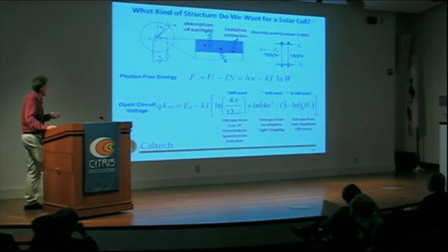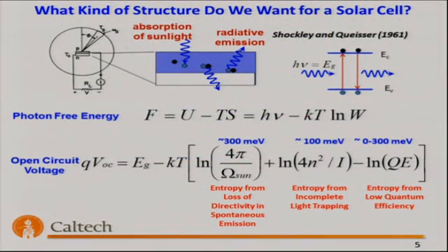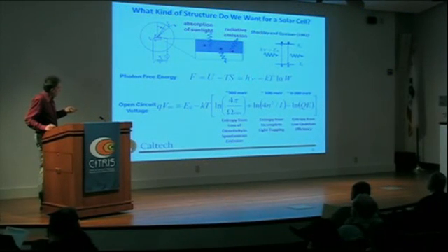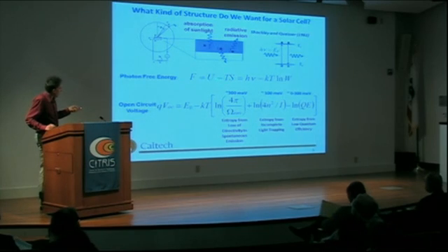And if we think about the factors that I showed here at the bottom, other than the carrier thermalization, we can express these in terms of a free energy associated with photons as they come in and are absorbed in a semiconductor. If I have a semiconductor with a reasonable quantum efficiency, that has a reasonable probability of radiative emission, then I can view this in terms of this exchange between absorption and radiative emission here in the energy level diagram across the band gap of the semiconductor. And I can frame this in a Helmholtz free energy picture, and I have the internal energy play the role of the internal energy for a photon absorbed at the band edge by either the photon energy or the band gap energy. They're equivalent without thermalization.